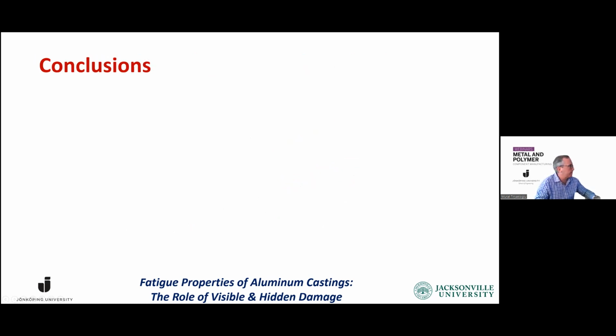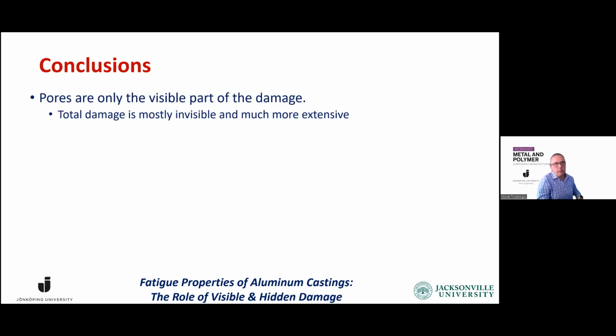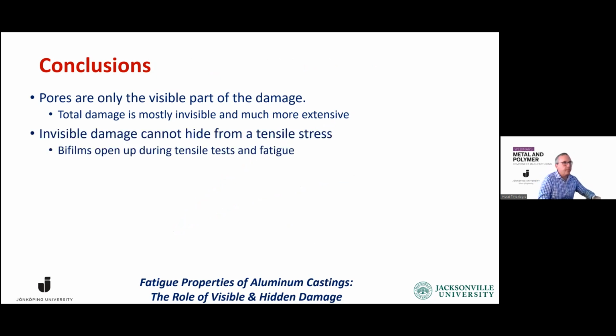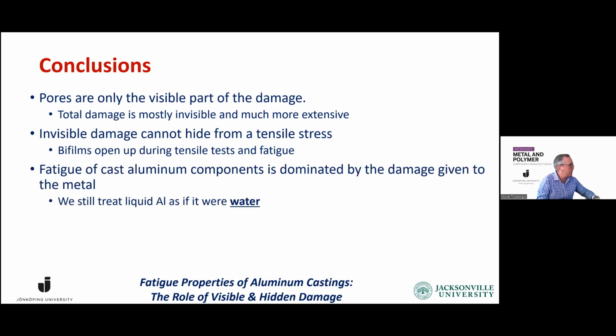So in conclusions, pores are only the visible part of the damage. The total damage is much more extensive. Invisible damage cannot hide from the tensile stress. Bifilms open up during tensile tests and fatigue. The fatigue of cast aluminum components is clearly dominated by the damage given to the metal when it's in liquid state. We still treat the liquid aluminum as if it were water, and that has to change.